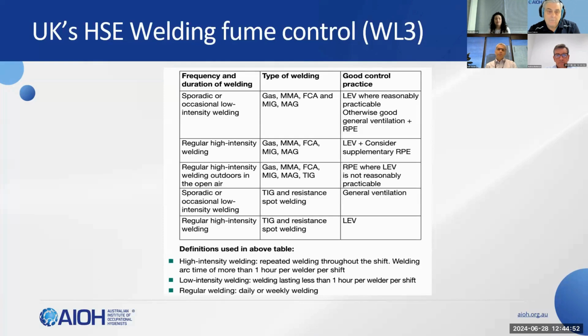In the reviews we've done, we advise inspectors as a general rule, not as an absolute rule, that if welding, or arc time, and it is arc time, is greater than 1 hour, then they should start looking for a control. A control needs to be introduced into that process. It's trying to equate with what we've seen so far, that generally for standard MIG welding in a relatively open area, more than 1 hour is likely to get above the standard. But as I said, that is a general rule of thumb.